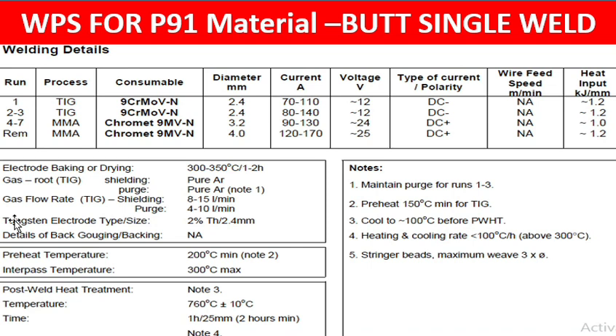Gas root: for shielding, you have to use pure argon for the root. When you are doing the root welding, the shielding is pure argon. For purge, also pure argon. Note one, what is mentioned? Maintain purge for runs 1 to 3. So we have to use purge for 1 to 3, and you have to maintain that purge, the pure argon.